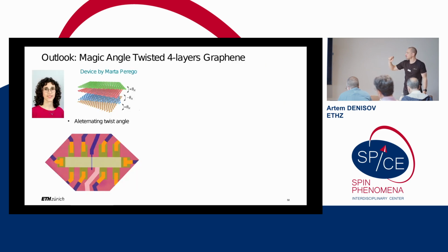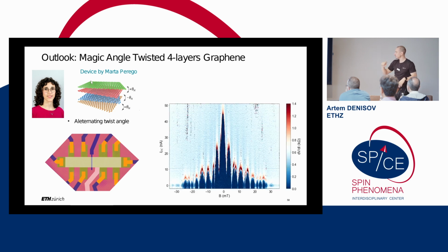Okay. And just a few words as my closing remark about our superconducting activity. We recently finished measuring a device made by Marta, which is a 4-layer twisted magic angle Josephson junction, shown here. You have 4 layers of graphene, so you can imagine it as 2 magic-angle bilayer graphenes on top of each other with a slightly different twist angle. This device acts as a very normal Josephson junction, and we can clearly see a very nice Fraunhofer pattern.